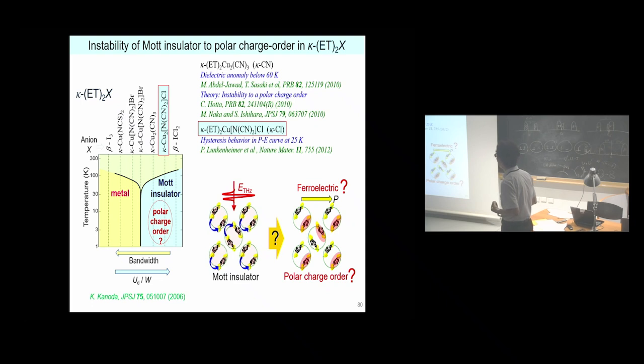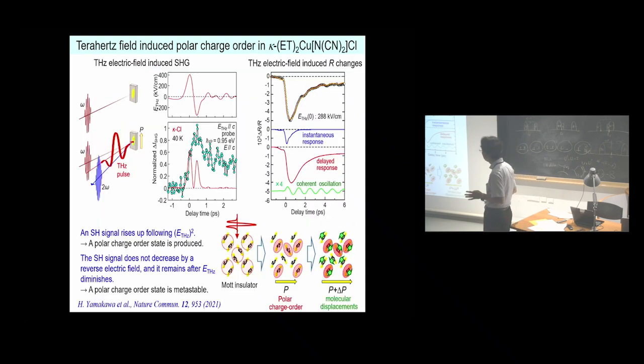Here I will show the result of this compound. To detect the polarization, we use second harmonic generation. By a terahertz electric field, the second harmonic signal rises following the square of the electric field, suggesting that a polar charge order state is produced. This second harmonic signal does not decrease by a reverse electric field at this time, and it remains after the electric field diminishes in this time region. This indicates that this polar charge order state is a metastable state.